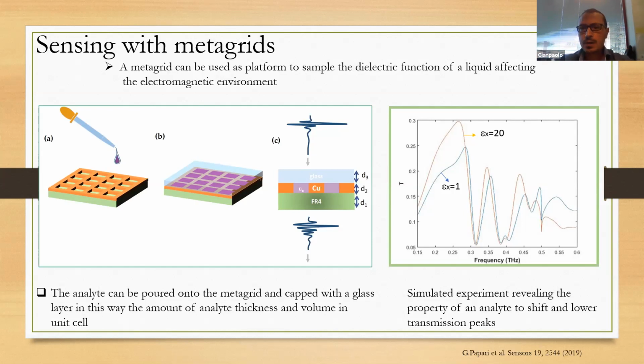The problem is that in order to create this structure, which is very good because now we have specific information on the volume in the unit cell of the analyte, we can also proceed to make some sort of retrieval processing in order to extract from the transmission of this very complicated structure just information on the dielectric constant. So, aiming to provide the right constraint to apply proper models to this system, we have lost signal to noise ratio. It's decreased because the higher the number of layers, the higher the losses. And so the information degrades.